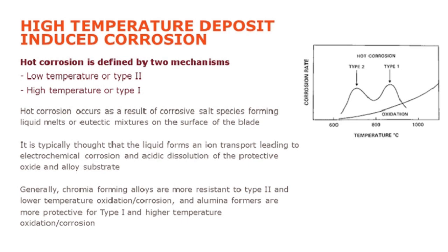Just a general note on alloys and how they tend to respond to this mechanism. Generally speaking, chromia forming alloys, so alloys which form a chromia oxide, are more resistant to type 2 and lower temperature oxidation and corrosion, and your alumina forming alloys are more protected for type 1 and higher temperature oxidation and corrosion. I also think it's sometimes debated whether hot corrosion reactions are deposit regulated, or whether they're regulated by gaseous composition or partial pressure of SOx or SO3. And in my view, I think there are several competing mechanisms, and it's quite a complex picture.